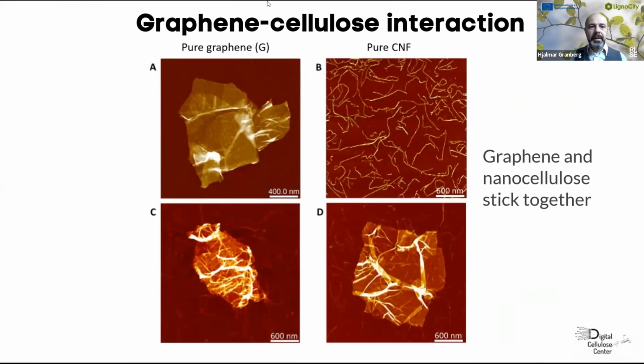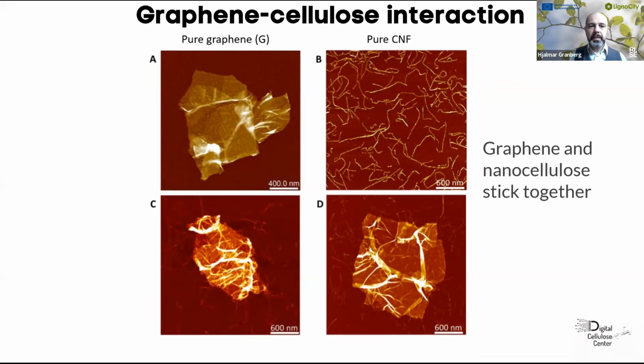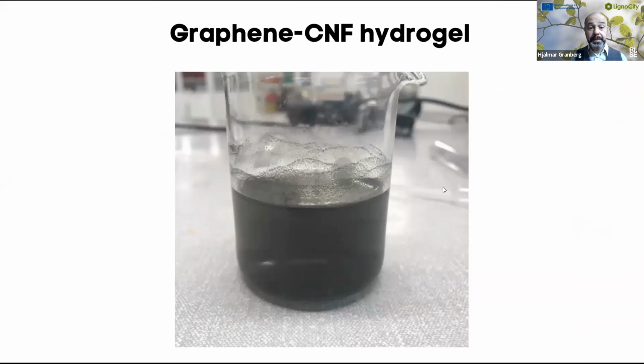But we can also look at the graphene cellulose interaction. So here you have a graphene flake. Many of these together makes up a graphite. And then the nanocellulose, as this one. This is hydrophobic and this is hydrophilic. If you mix them, these will stick to the graphene. So you can end up with a lot of synergetic effects. One of these effects is that you can actually disperse graphene in water. And when you can disperse graphene in water, you can also make water-based processes such as paper.